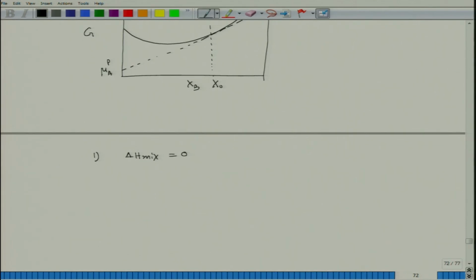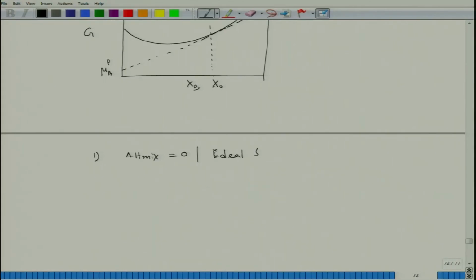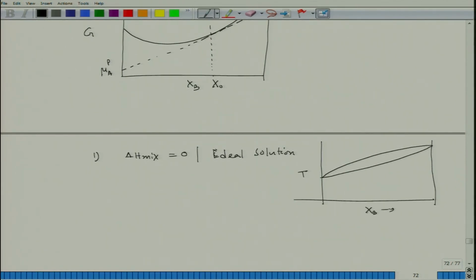And accordingly, we have done all sort of calculations in order to find out phase diagram, because that time to solve that mixture, those particular situations were a little easy, because we did not have to consider ΔHmix. For example, in this case, which is absolute ideal situation, ideal solution, we have drawn an isomorphous phase diagram. And in that case, we have taken a solid liquid isomorphous situation.